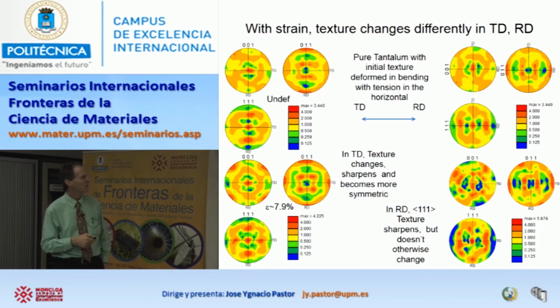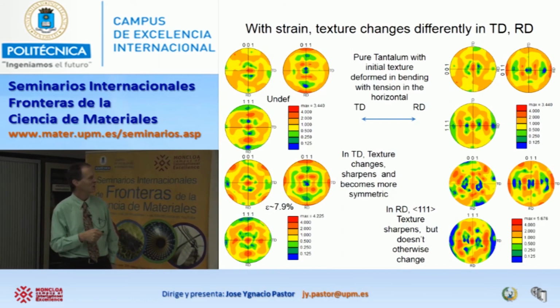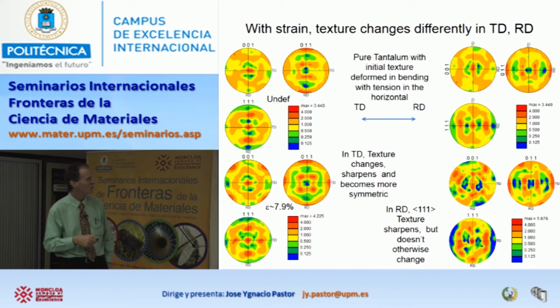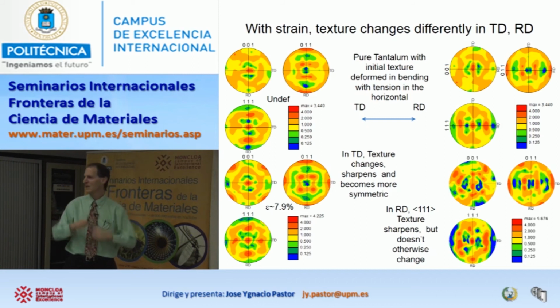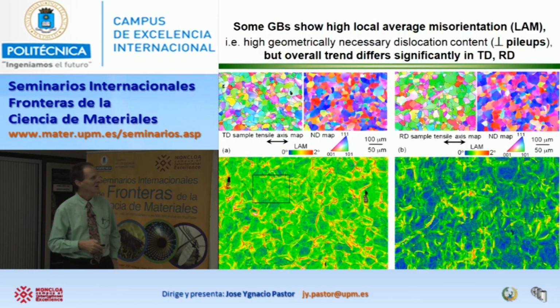And then pole figures of the same information show that if I deform in the transverse direction, the texture changes a little bit. If I deform in the rolling direction, then the texture doesn't change so much, because I'm deforming in the same way that it was already rolled, which means there really isn't any difference in how the deformation is continuing. Well, here's the interesting part.